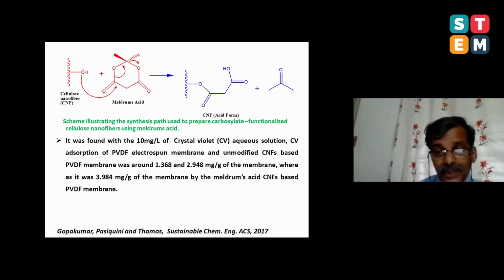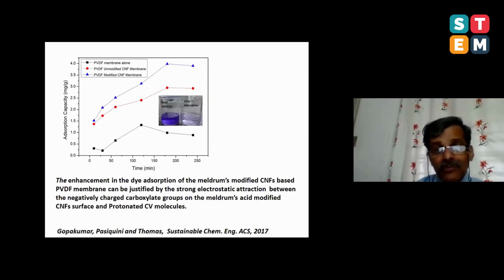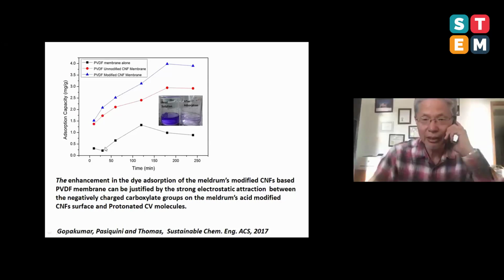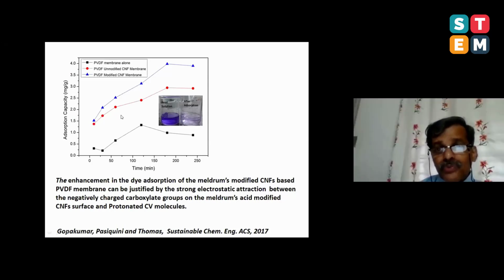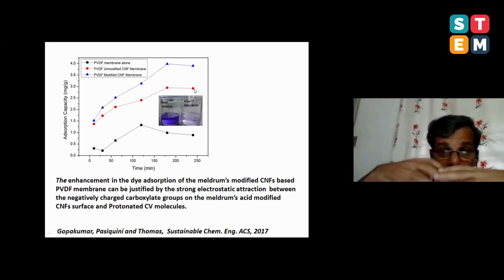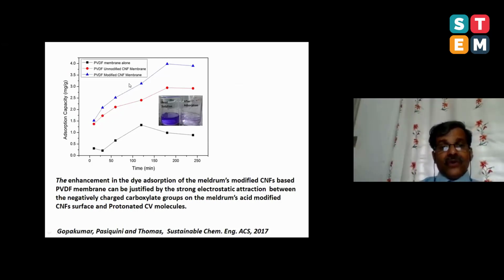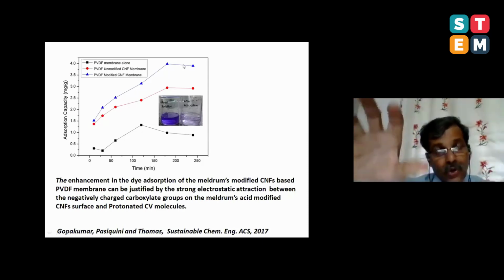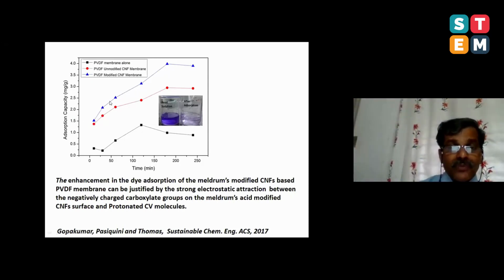And when you do such chemistry, there is a beautiful separation process. Look at this, this is a commercial filter that you get from the market. When you use a commercial filter, if you want to remove the dye, the total process is something like this. If you spray the filter with nanocellulose dispersion, look at the efficiency, it has increased. And if you spray with chemically modified nanocellulose with COO minus group, look at the separation efficiency, it has increased